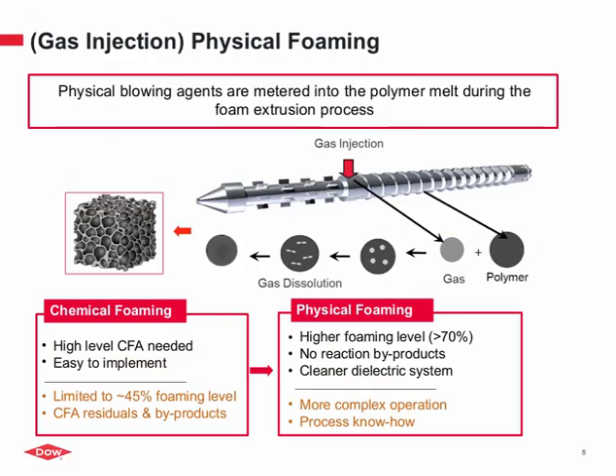Just a brief background of how the process generally works. It is generally a single screw system. Of course, lines are different. They are tandem lines and so forth. But for a high-level description, what we have is the polymer itself, or the polymer compound that is properly nucleated, that is fed into the extruder, melted and pressurized, and pumped to a high-pressure zone where the gas is injected. This is the foaming gas itself.